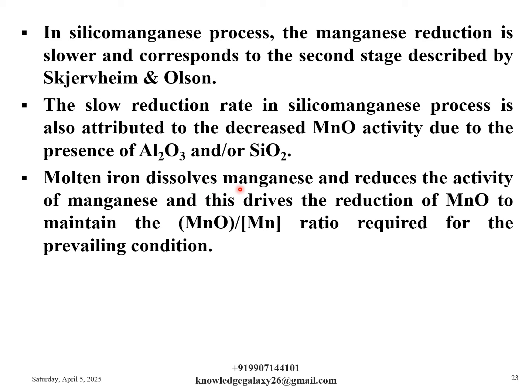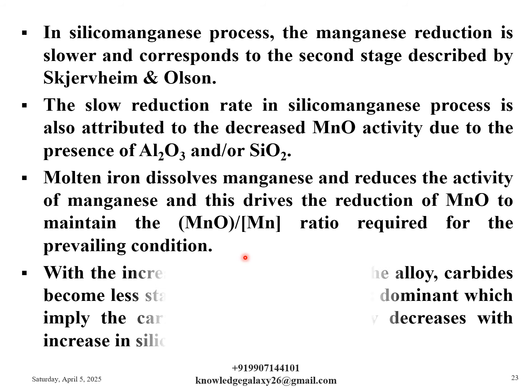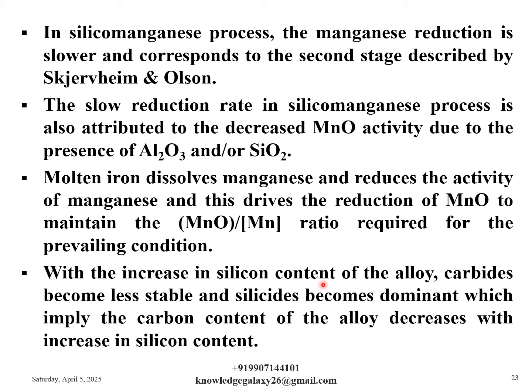Molten iron dissolves manganese and reduces the activity of manganese, and this drives the reduction of MnO to maintain the MnO by Mn ratio required for the prevailing condition. With the increase in silicon content of the alloy, carbides become less stable and silicides become dominant, which implies the carbon content of the alloy decreases with increase in silicon content.